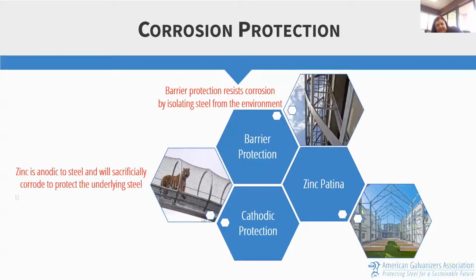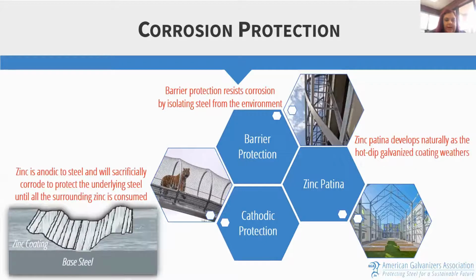As we talked about at the beginning, the most common reason that hot dip galvanized steel is chosen is for its corrosion protection. It really provides three levels of protection. It provides that basic barrier protection that basically any coating used would provide by isolating the steel from the environment. But more importantly, it provides cathodic protection, which means that the zinc is going to sacrificially corrode to protect the underlying steel. As long as there is zinc on the piece, it's going to corrode and prevent the steel below it from corroding.